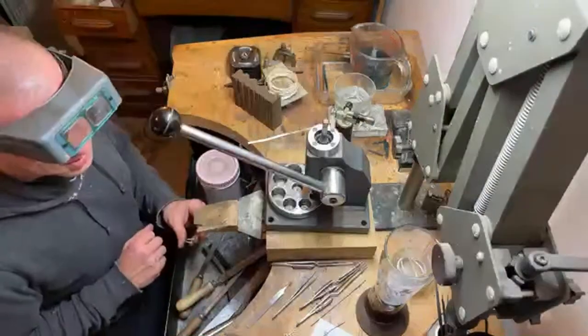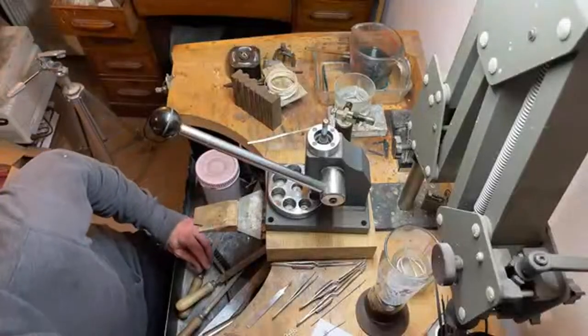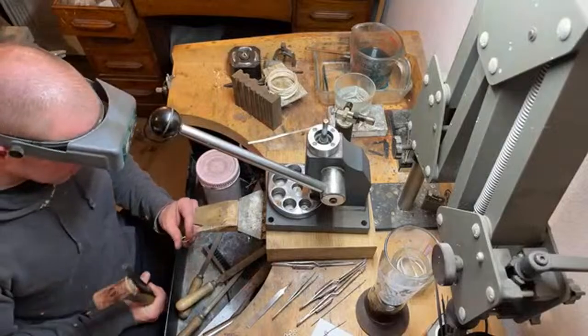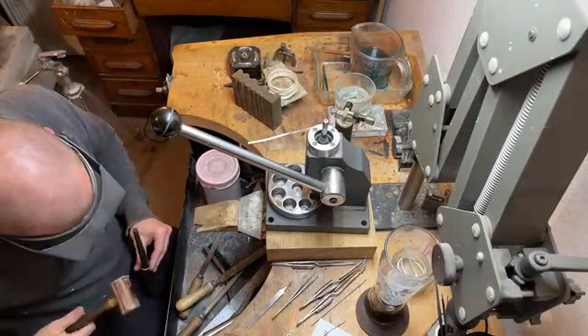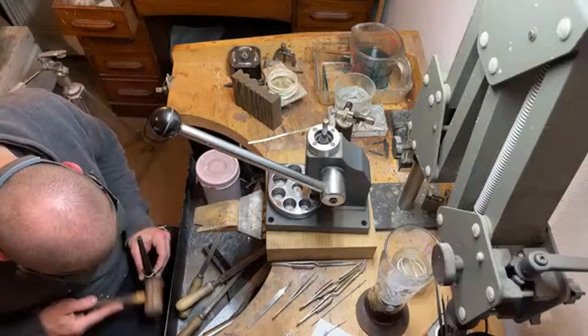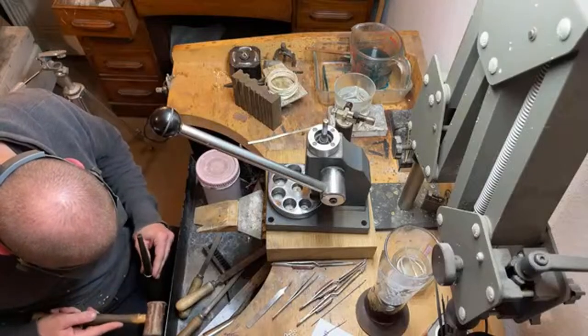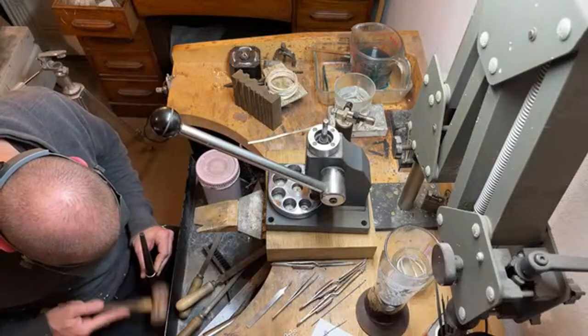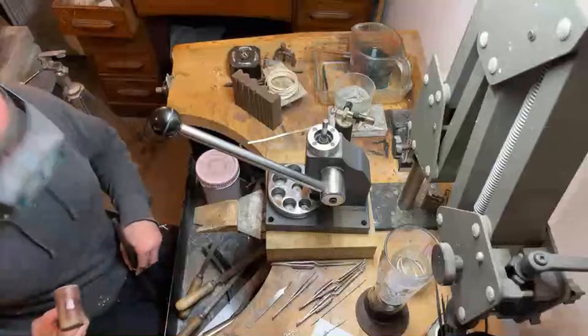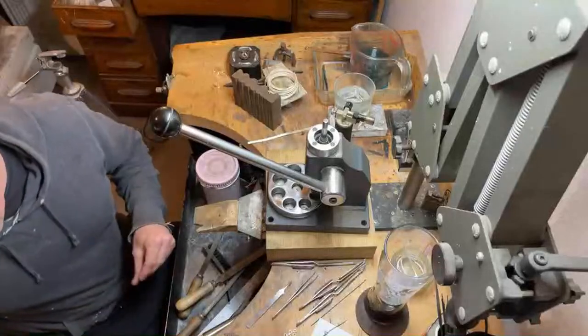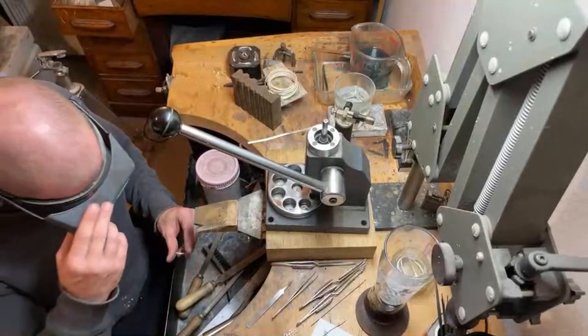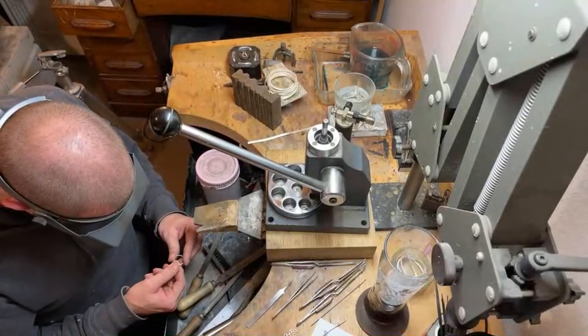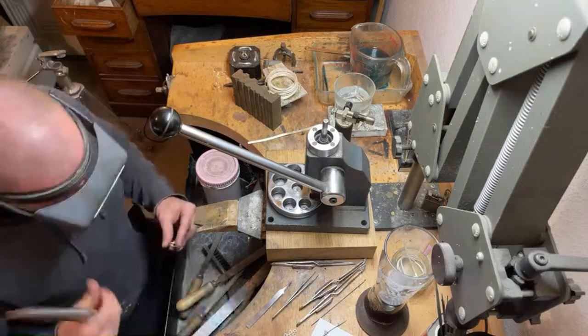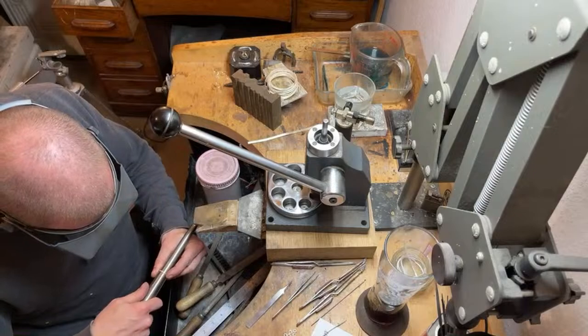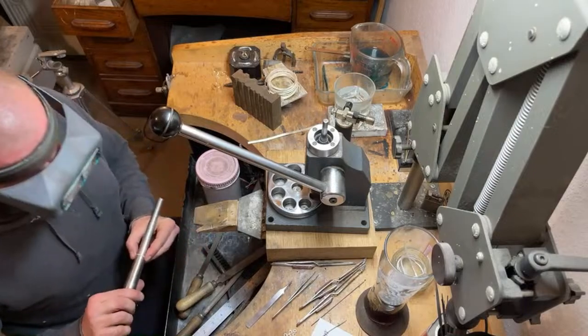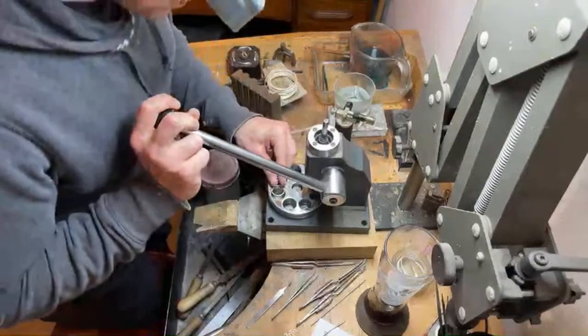With this D-shaped wire, it just doesn't work. The inside ends up hotter than the outside all the time. It must just be something to do with the shape and the surface area. Physics and science beyond my pay grade. But despite my trying to heat up the outside, the inside's hotter, and therefore that's where the excess solder ends up. I've got virtually none on the outside. Right, W and a half, which is great. You can size that down to a W.